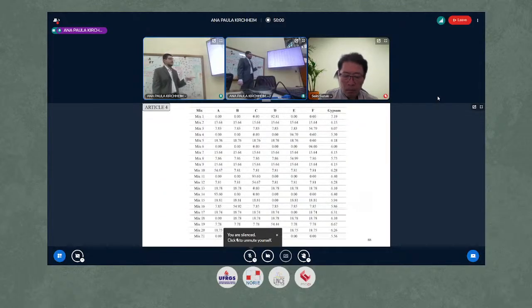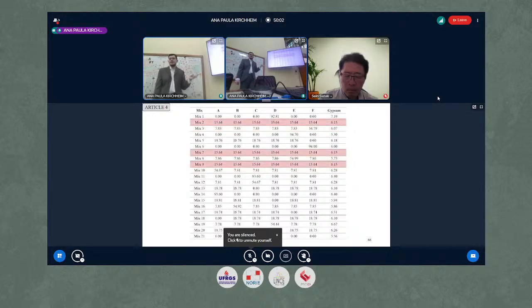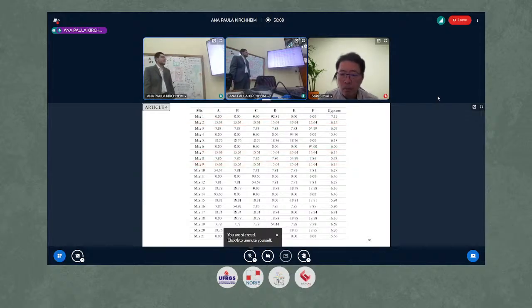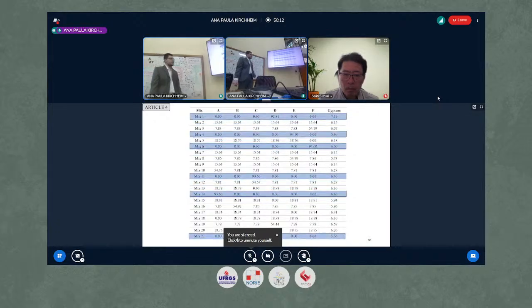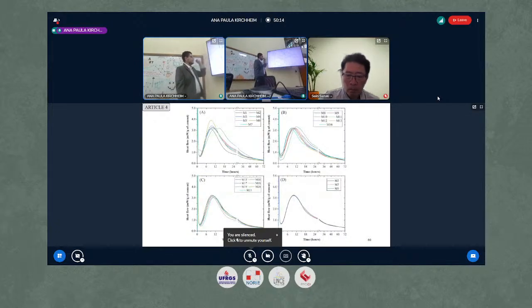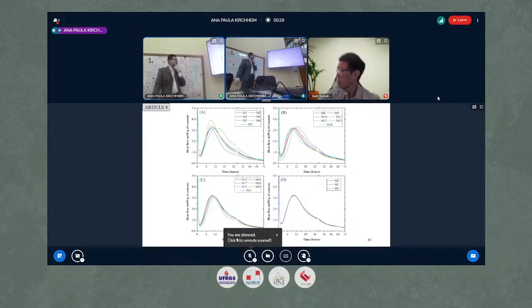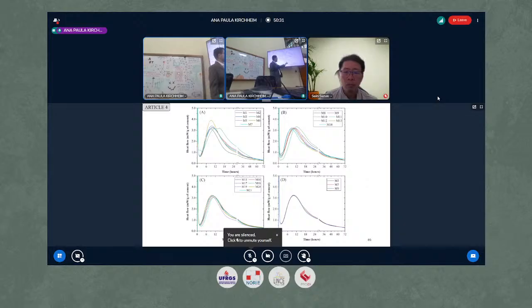So here are the 21 mixes. We have 3 of them that are equal, the centroid, to see the variation in the error in each measurement. We also have 6 of them that are only 1 clinker. So here's the calorimetry result, great variation, in length and time. And here we saw the error of the calorimetry, because we have 3 mixes that are equal, but I ran them on different days and weighed them on different days, and we see the error. So this variation is indeed significant.